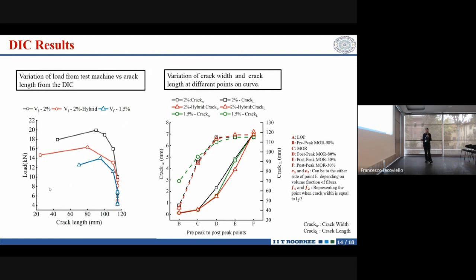So if we correlate these results with crack width and crack opening, it is interesting to note that in the load CMOD, the 2% results have higher peaks. But as far as the crack length and crack width are concerned, we have lesser crack length and crack width in the case of hybrid combination. Because in hybrid combination, there is a dual scale mechanism that is happening.